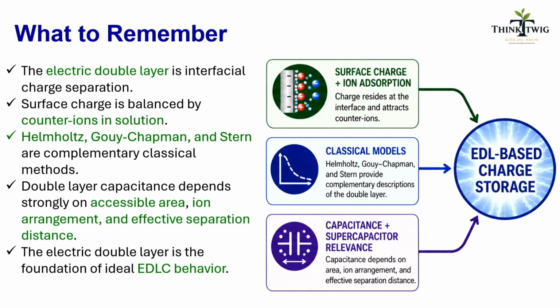Helmholtz described this interface as a compact layer, and Gouy and Chapman explained that thermal motion creates a diffuse ion distribution, and Stern combined both ideas into a compact region followed by a diffuse region. In a real nanoporous carbon electrode, the capacitance also depends on the accessible surface area, pore size, ion size, solvation, desolvation, and electrolyte conditions.